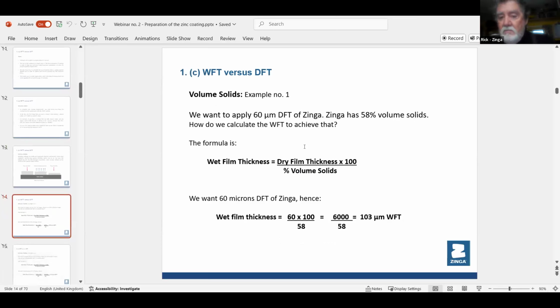So here we have a little formula for you. So there's your formula. To calculate the wet film thickness, you take the dry film thickness that you want to achieve, multiply by 100, and then you divide it by the volume solids. So if for example, we say, okay, on all these big sheets, they're going to be welded. So you only want 60 microns of Zinga. So you take 60 microns times 100 equals 6,000, and then divide it by 58, which is your volume solids content in Zinga. And you'll see this on your data sheet. Zinga's got 58% solid inside that wet film. And there it tells you 103 microns.